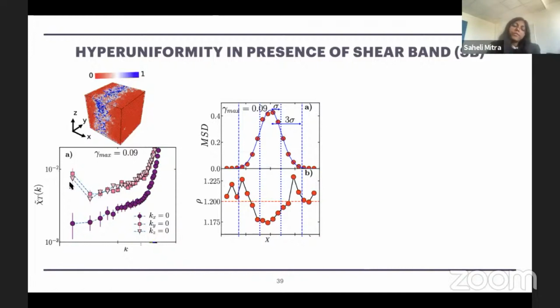So we now confirm that the upturn that we had seen above yielding is because of the shear band present in the system. Now we are interested in what exactly is happening, from the hyperuniformity perspective, in different subvolumes of the system in the presence of a shear band. So for example, we now put some observation windows in the shear band regime, in the part outside of the shear band, and in the part that includes the interface between the shear band and the outside regime.